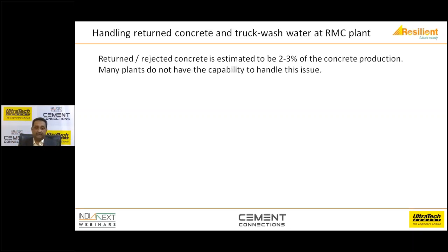If you look at any ready mix, on average 2 to 3% of concrete production is returned, rejected, dumped, or diverted. This is the thumb rule. If you can imagine 5,000 cubic meters in a day, then you can expect somewhere around 100 cubic meters of concrete in this category, which may come back to the plant because of a pump failure or the redosing of admixtures or whatever the problem is.